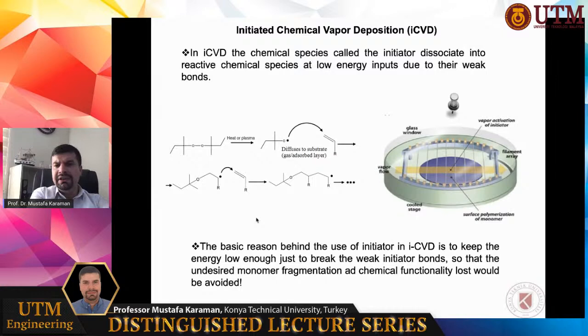In iCVD, chemical species called the initiator are fed to the system, and they dissociate into reactive chemical species at low energy input due to their weak bonds. On the right-hand side, you can see the general view of a large-scale iCVD chamber. It is a vacuum chamber, and it contains a filament array. Here you can see the filament array, and at the bottom, you can see the circular substrate. It's usually a silicon wafer. And the reactor has a cooling stage at the bottom.